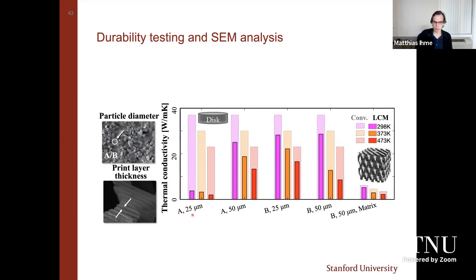And the second parameter is the layer thickness. Remember, the first layer thickness that I showed you was somewhere around 25 micrometers. This is our sintering layer. By modulating this between 25 micrometers and 50 micrometers, we can get different thermal properties, and this makes this rather interesting. So the summary here is illustrated.